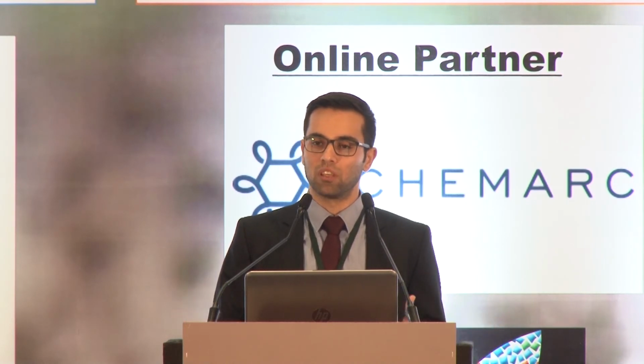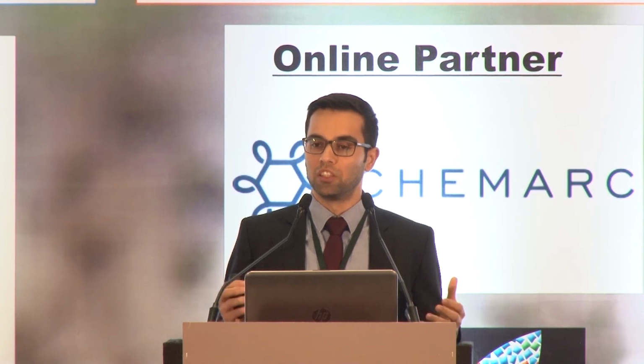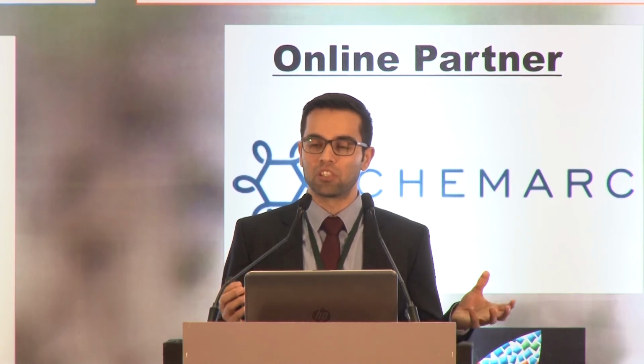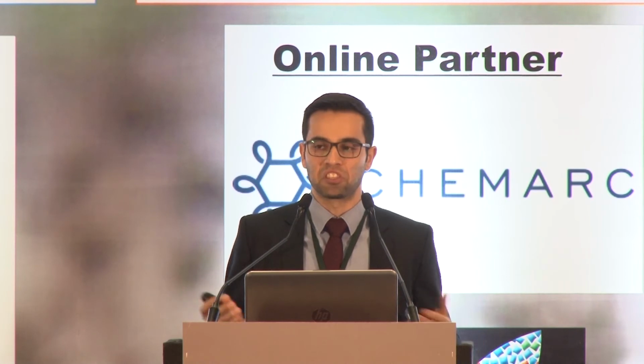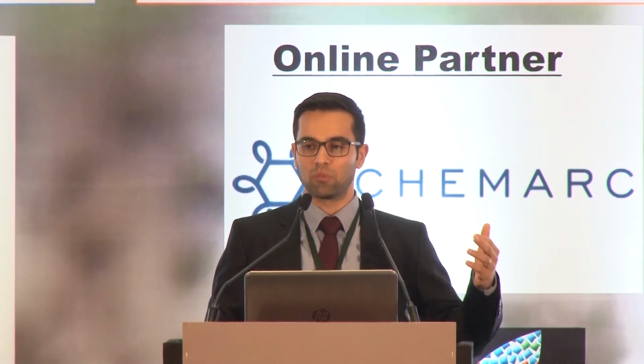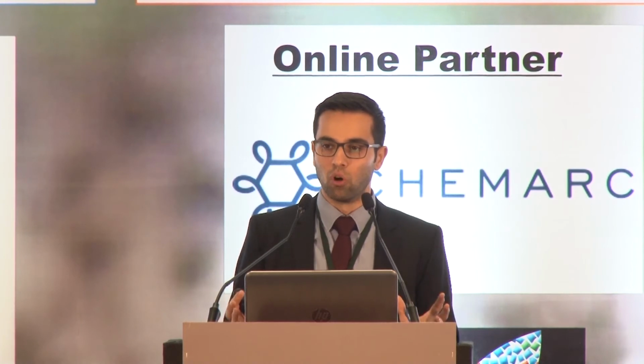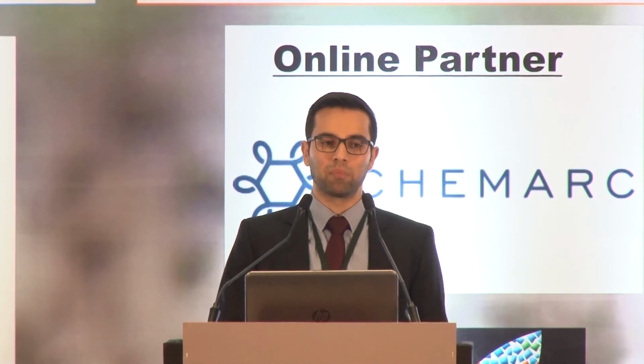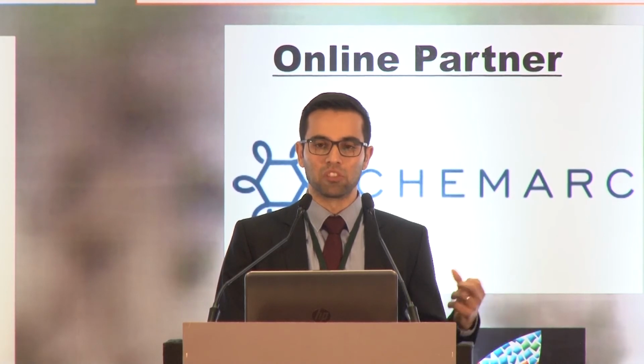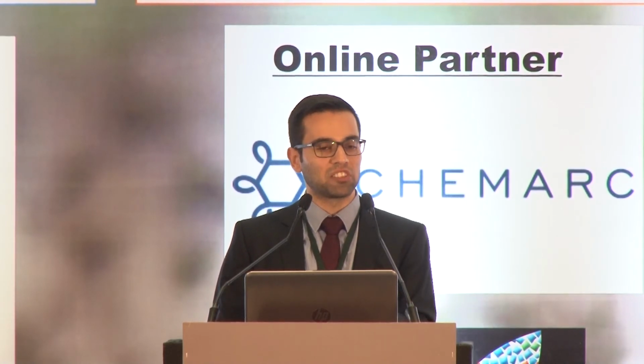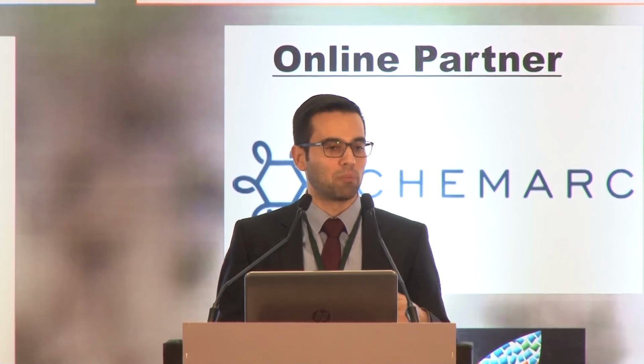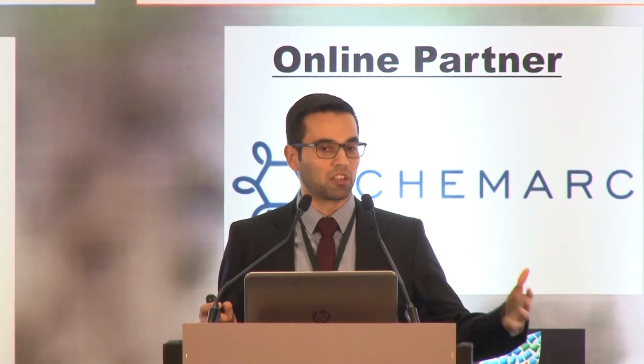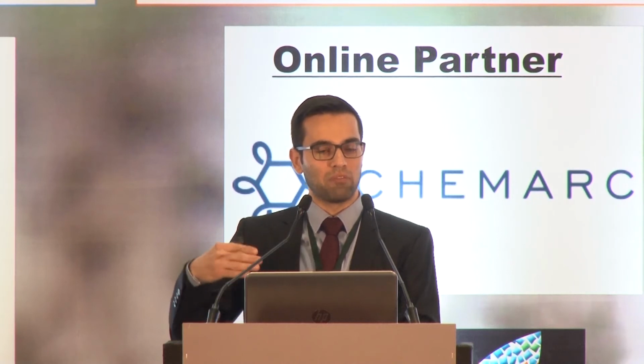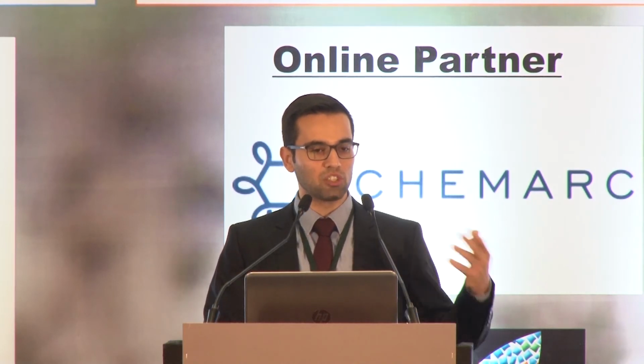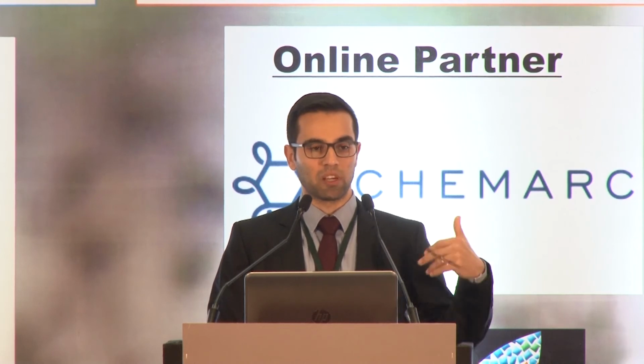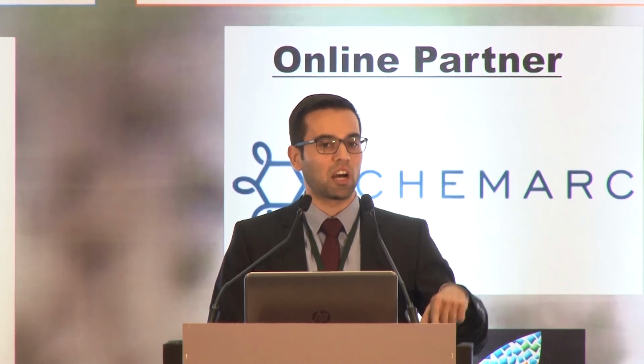And now we're cooperating with a very well-known institute in Germany to measure the abrasiveness, as compared, let's say, to glass fiber at 30 to 60 weight percentage, and to other fillers which have lower hardness. So we're trying to do all of this. But my message here: to describe the abrasiveness of the material using the Mohs hardness, that's unfair, because there are so many other factors: morphology, particle size, surface treatment, and viscosity in the compound. So if you have a compound with double the viscosity, and you're doing injection molding or extrusion, you will have much more abrasiveness, even if it has lower Mohs hardness.